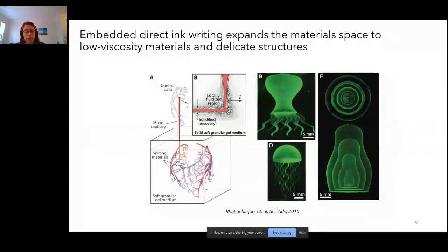The way that this works is you have a print bath that is full of a support fluid. Usually that fluid will have a yield stress and it'll be shear thinning just like those materials that I talked about in the last slide. So things like carbopol hydrogels or laponite hydrogels will be good support baths. You embed your nozzle into that bath and then write out continuous filaments for embedded direct ink writing, or you could print out droplets for embedded droplet printing.